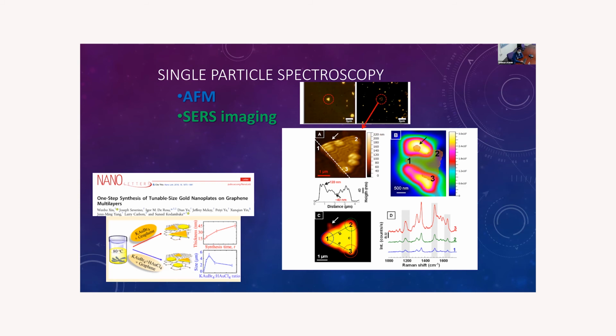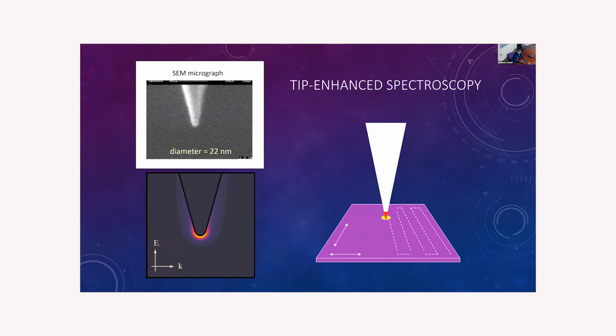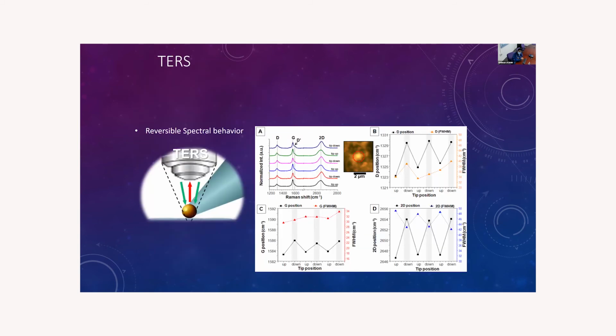But the focus of this article was to measure the tip-enhanced spectroscopy of the system. At that point, I start to know that when I make contact with the tip, the tip is a conventional AFM tip with a gold nanoparticle on the tip of the probe. So when this tip interacts with the system, I start to see that there were a lot of changes in the optical properties, in the spectral properties of the system.